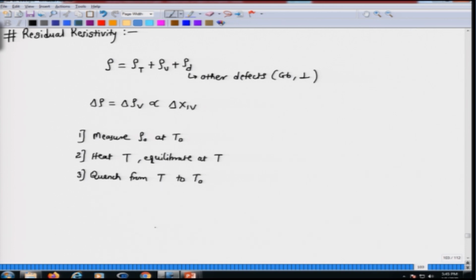Whenever we are doing a heating or cooling, as the temperature changes, the system tries to achieve the equilibrium vacancy concentration, and this is done by diffusion of vacancies to sources or sinks. If vacancies have to be created, there are sources. Grain boundaries, dislocations and surfaces act as sources.